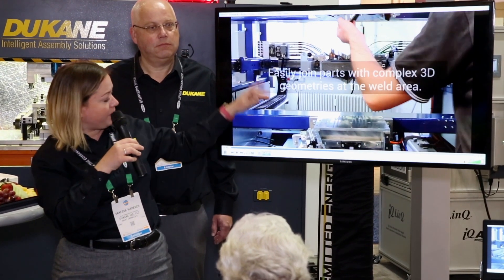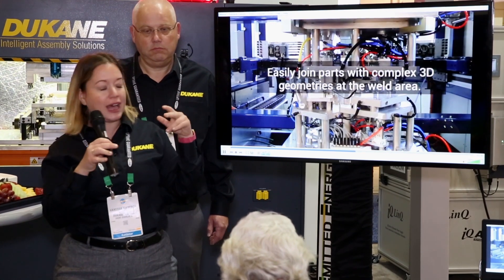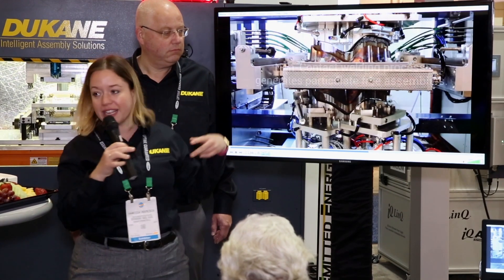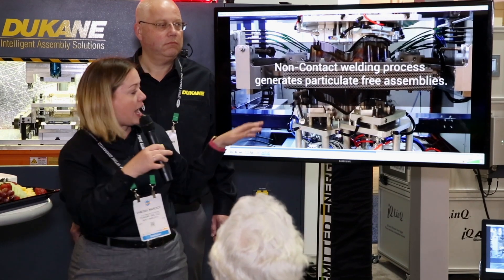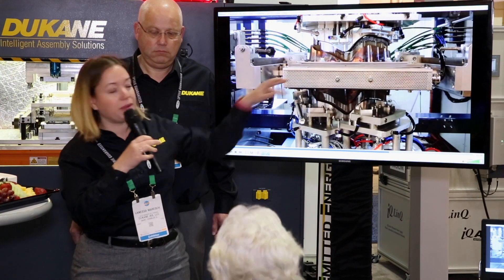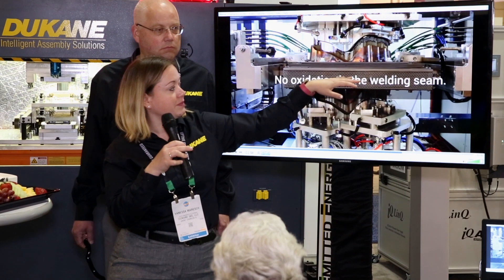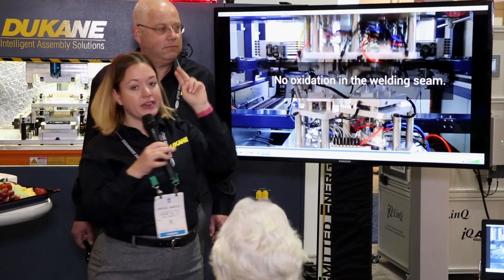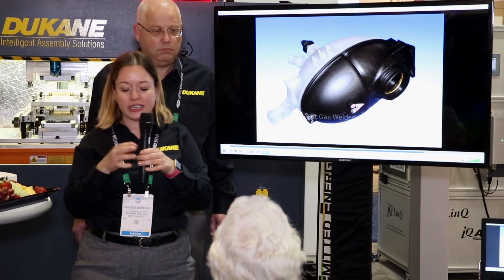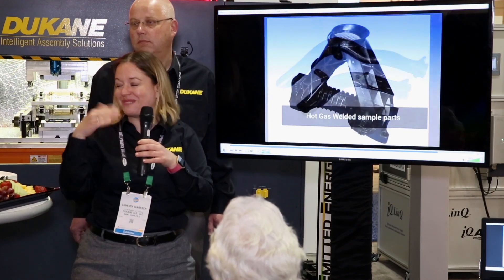The fixtures in the video are nearly the same principle as the fixtures from hot plate welding or infrared welding. So we have sensors in them, we have a clamping function in them, and we cool the fixtures. The heating element will be heated up electrically — we have heating cartridges in it. And because of the nozzle plate technology, we can weld very, very complex parts, and if the part has some tolerances, we can bend the nozzles to weld the part everywhere.